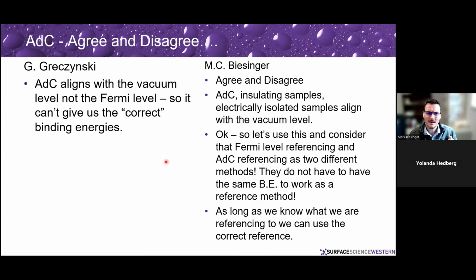And so having the correct binding energy, what does that mean? As long as you're referencing to the same thing, and when you're reporting, you're saying, okay, I'm reporting to adventitious carbon at 284.8, the aliphatic peak of that, then it works. And so these are two different referencing systems, and we have to accept that because we really don't have an alternative for insulating samples. There's not one that's universally easily accessible, but we have to do it correctly every time.